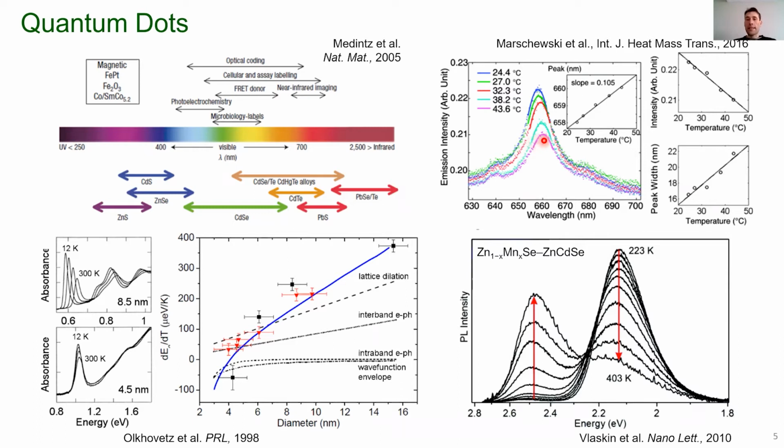and absorption. And this is what was done here with these quantum dots that were doped with some manganese, and the fluorescence from this ion was opposite in direction. So the fluorescence of the quantum dot is going down as the temperature goes up, and vice versa for the ions. And so you can reference these two emissions to one another, and so you now are immune to thermal equivalent noise, which in this case would be due to absorption or scattering.